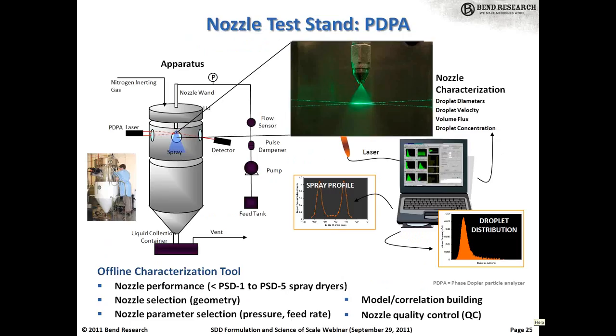So at Bend Research, we actually measure the droplet size directly using a phase Doppler particle size analyzer installed on an inerted chamber that's designed to prevent drying. So we're really just going in and measuring the droplet size directly. And we can oftentimes do this with the placebo solution where we match the viscosity of the active solution. So a lot of times early on we can just select a nozzle directly by measuring these different droplet sizes under different conditions. Of course, this also begins to lay the groundwork for future correlations between things like nozzle geometry, nozzle pressure, and the solution properties like viscosity.